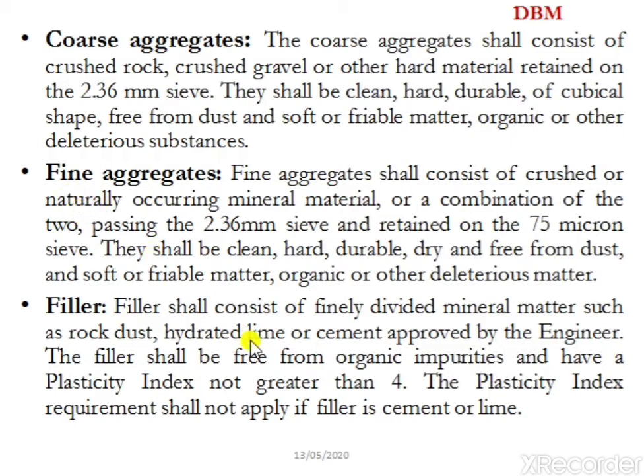And next is fine aggregate. Fine aggregate shall consist of crushed or naturally occurring mineral material or a combination of the two, passing the 2.36 mm sieve and retained on the 75 micron sieve. They shall be clean, hard, durable, dry and free from dust, and also soft or friable matter, organic or other deleterious matter. So the material which passes through the 2.36 mm sieve and is retained on the 75 micron sieve is used for the construction of DBM.